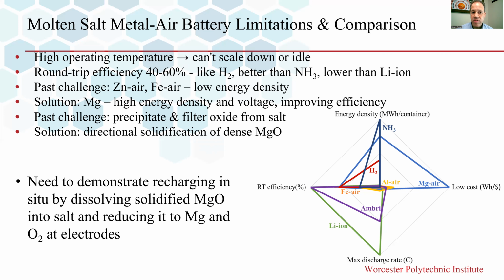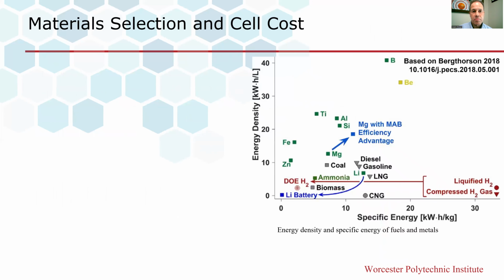We have demonstrated the ability to withdraw the magnesium oxide using directional solidification. The last piece in this is to demonstrate recharging in situ by dissolving solidified magnesium oxide and reducing it to magnesium and oxygen at the electrodes.